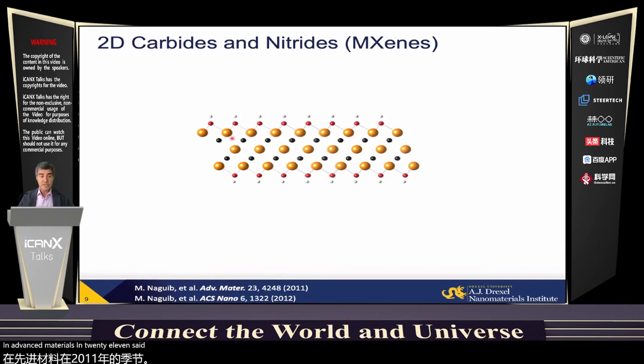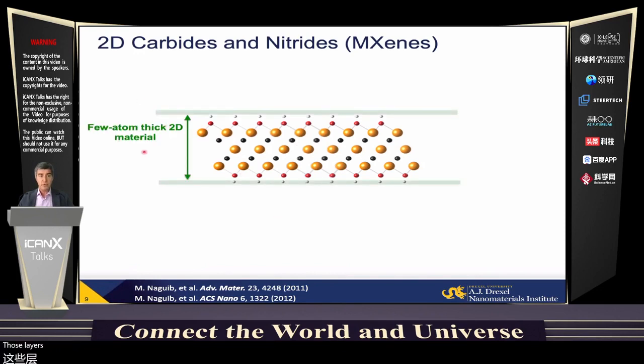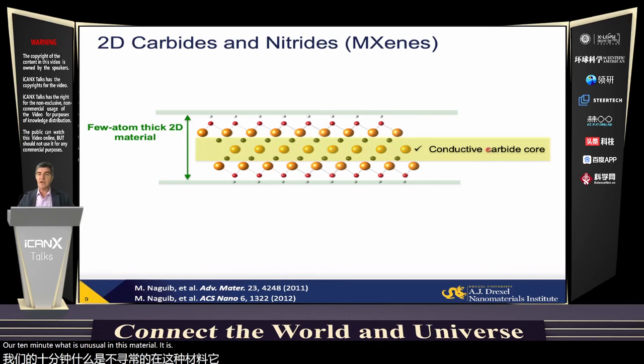What you see here are these golden spheres, which are actually metal atoms, titanium. Those layers are a few atoms thick, just like other 2D materials here. The golden ones, actually, titanium, is the metal, M. The black one stands for X, in this case carbon. And I'm showing it with OH termination. What is unusual in this material? It has a conductive carbide core.